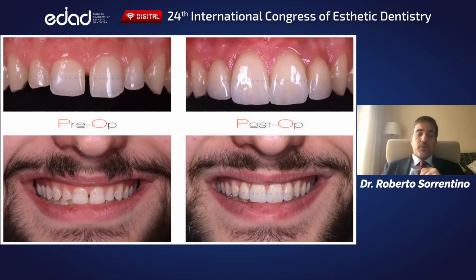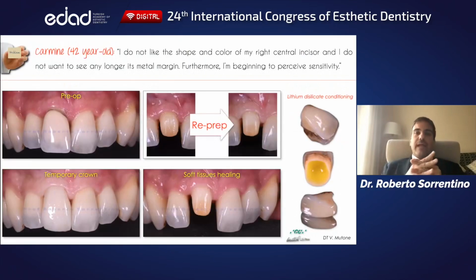The same approach can be used with full coverage lithium disilicate crowns as well, as in this re-entry case on a previous metal ceramic restoration, in which I chose a lithium disilicate press single crown layered buccally, but left monolithic on the palatal functional surface, so as to avoid any risk of chipping.